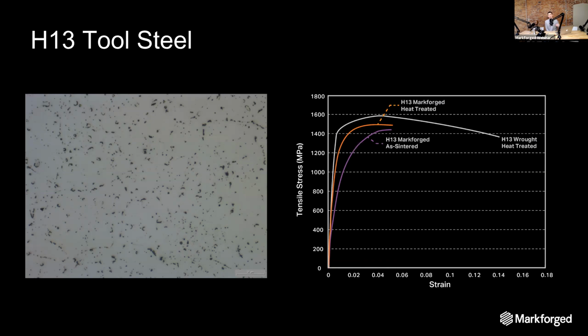Alternatively, if you temper it a little bit cooler, say somewhere between 500 and 530 C, your Rockwell hardness will rise to in the neighborhood of 50. This is general metal, not specific to ours. And so you can get a little bit harder of a steel. What you get there is that the toughness of the material, by like an Izod notched standard, would drop significantly. So tempering it to a higher temperature gets you a lower hardness but higher toughness. So that's kind of just an overview of the space there. There's plenty of literature out there about tempering temperature versus toughness and hardness. If you want to use H13, and I'm sure you already do, you can look into it. Our stuff generally holds true to what those standards are.